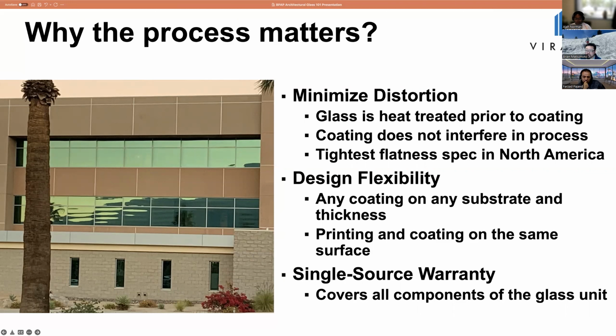We're heating a uniform substrate, versus the regional fabricator who's heating a piece of glass that on one surface has a low E coating. And what's a low E coating supposed to do? It's meant to reflect heat. So it makes it a little more difficult for them to get that glass to the right temperature. If they don't, the most common mistake is that it gets overheated and then it sags in the rollers, it hits that quench, and now you've induced roller wave distortion into the glass.